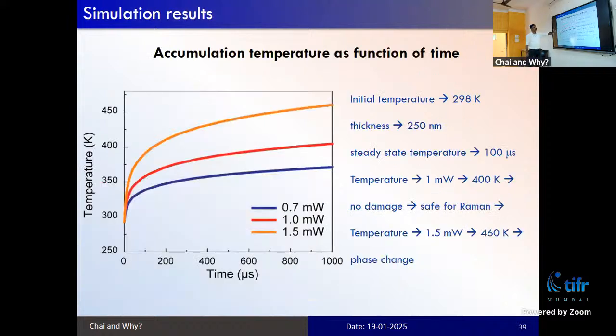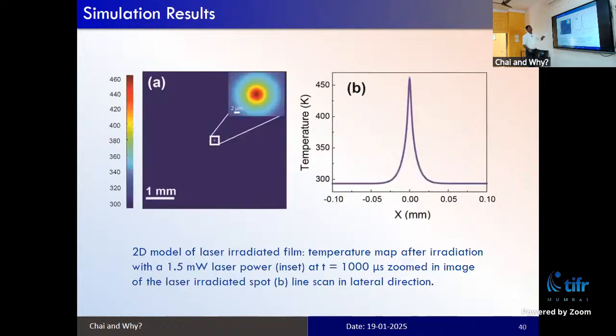So this is the temperature accumulation as a function of time. At 0.7 milliwatt, the temperature is below 350 K. When you raise the power to the phase transition condition, it reaches a temperature of 460 K. At this temperature, the phase transition is happening. If you plot it, since the laser beam is a Gaussian beam, the center point is at the highest temperature and it decays outward. The highest temperature is around 460 K, by which we have calculated the optimum temperature required for the phase transition.